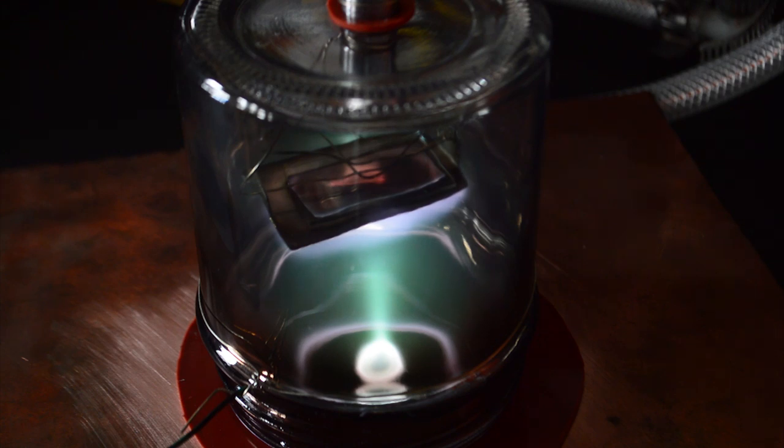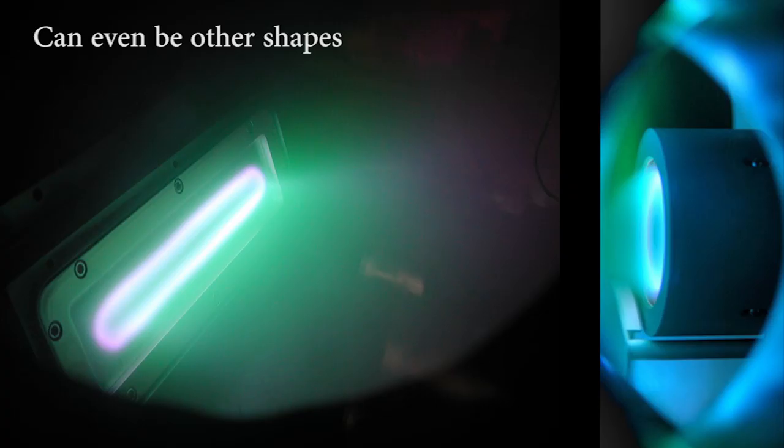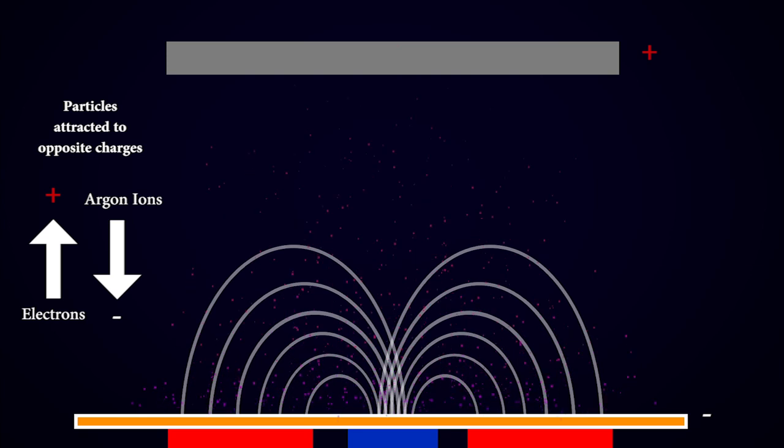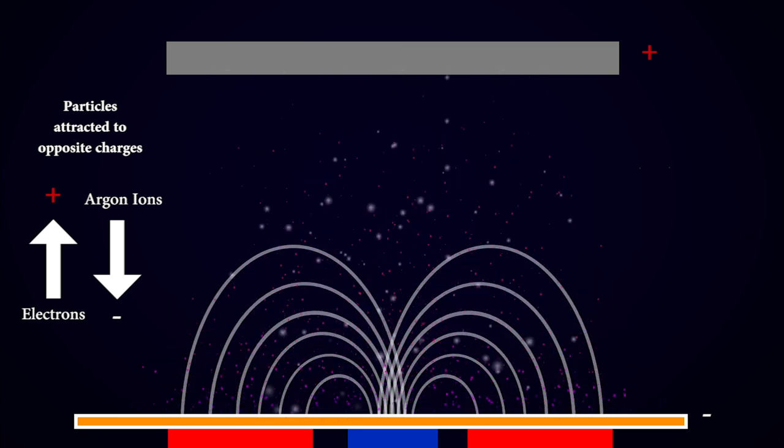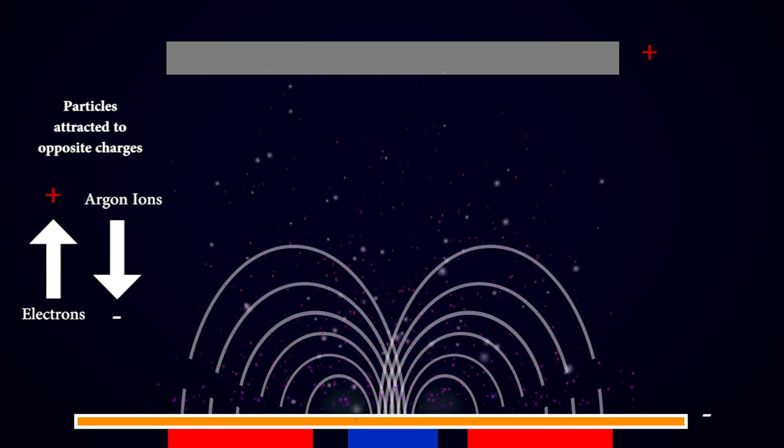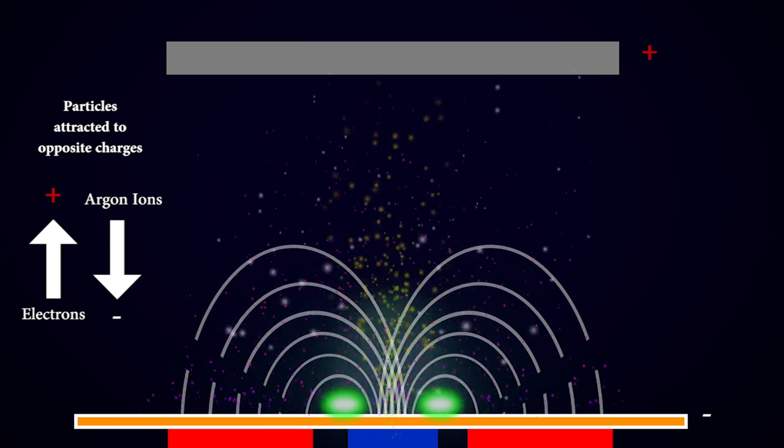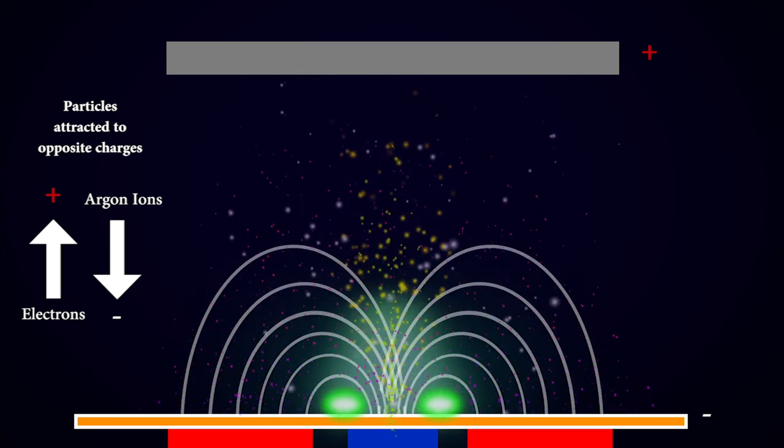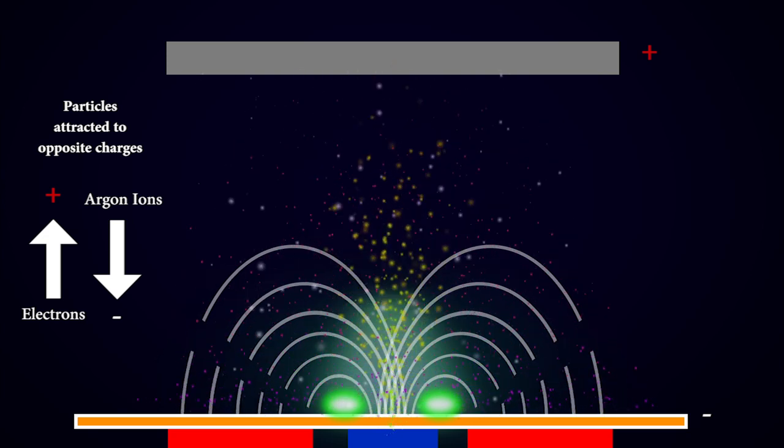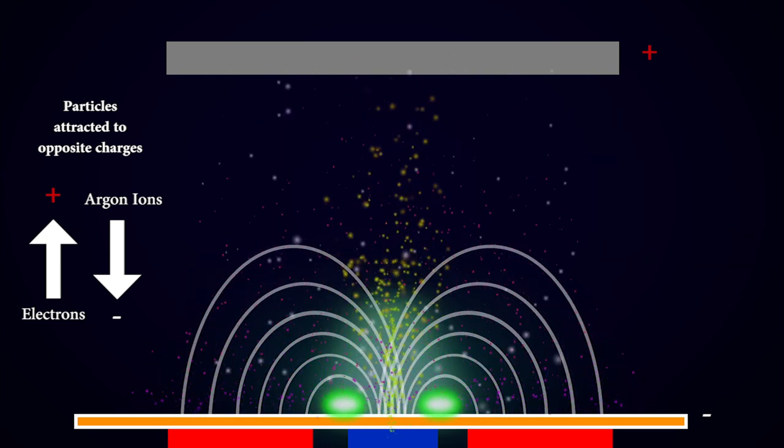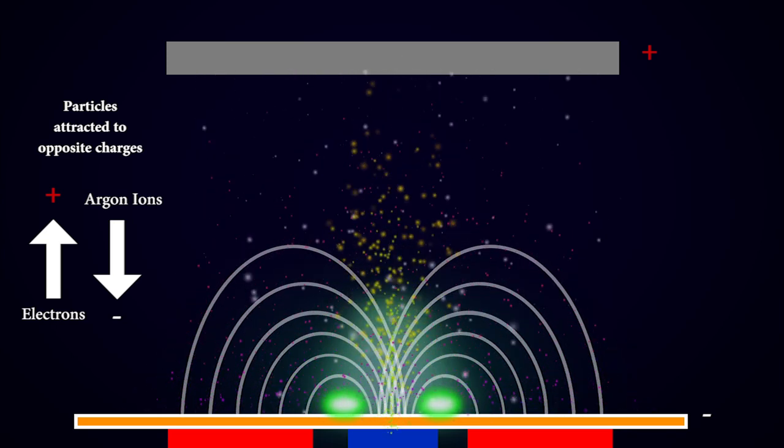Mine formed a small 1cm or so ring, but normally you choose magnets that give you a larger ring. The idea here is that the inner magnet is pointing in the opposite direction to the ring magnet, so the field coming out of one curves and flows directly into the other. This makes this sort of M shaped field where you end up with this kind of dead zone as the field lines approach perpendicular to the magnet they're coming out of. The plasma is pushed and pulled by the magnetic field, but in the dead zone it can all concentrate, and is then held in place by the surrounding field. So you get this donut of concentrated plasma that's right in contact with the metal or material you want to sputter.